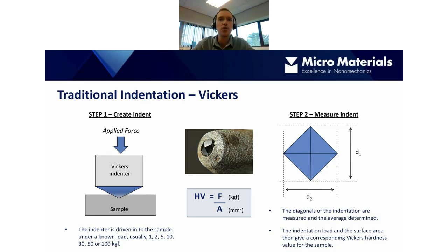And then step two is to measure the indent. After the indent has taken place, we use the optical microscope to measure the diagonals of the indentation. So the two diagonals, and then the average is determined. From that, we can get the surface area of the indentation. And quite simply, the Vickers hardness value is the force divided by the area, and that gives us an HV value. So this technique has been going for well over a century, and is commonly found in pretty much all material science and engineering departments.